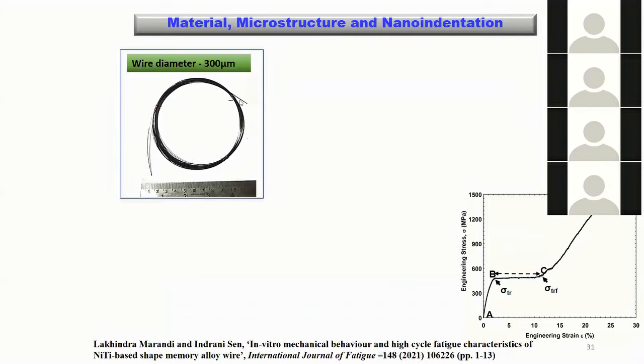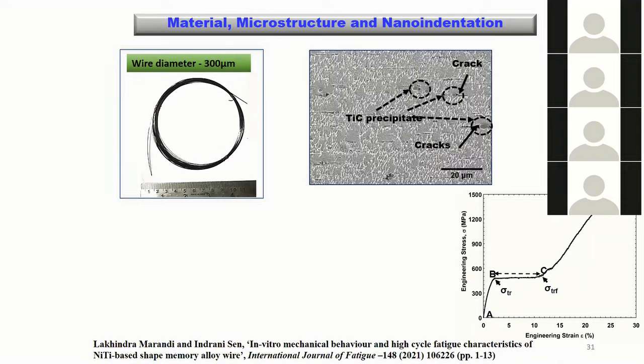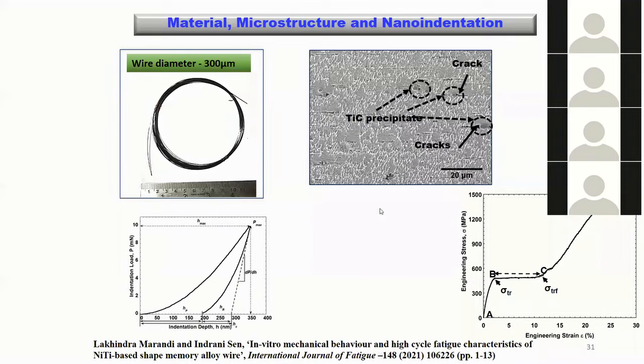Now this is the wire, starting with a cold drawn wire, and this is the typical stress strain diagram for this wire. Okay, you see that it shows some elasticity, and then there is a nice pseudo-elastic plateau, and then there is martensitic deformation and so on. And we have also shown that this is pseudo-elastic. Slowly we'll come to that. Our focus, however, is to evaluate the properties in a biological atmosphere. So initially we looked into the microstructure of the wire. This is the cross section of the wire, and we can see that there are some cracks and some precipitates forming in the wire.